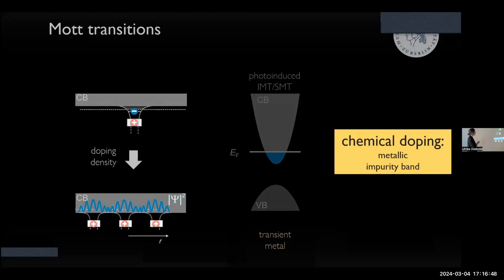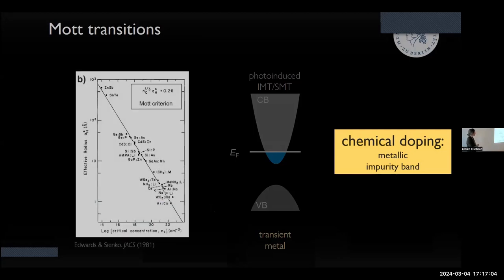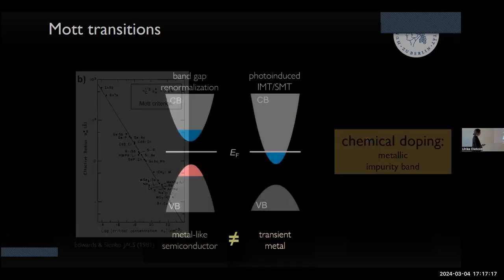Here you have shallow donors and you enhance the doping density, and then the electrons start talking to each other, they delocalize, and a metallic impurity band is being formed that is partially filled, and you can have conduction. This is happening in many, many semiconductors, and so you have the doping concentration, and then you have an effective radius of the dopant that defines this criteria.